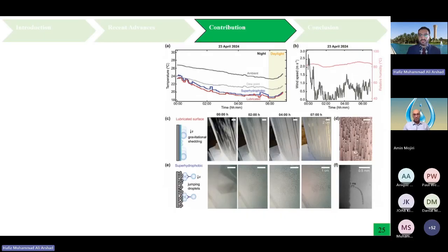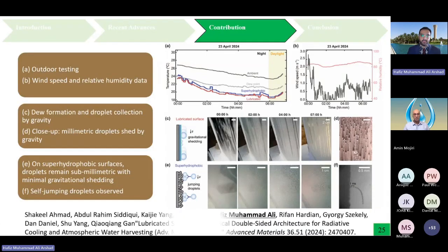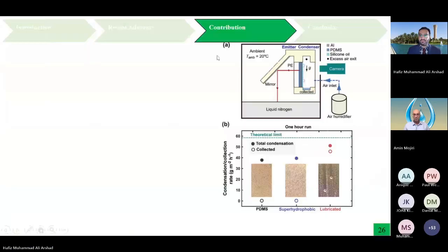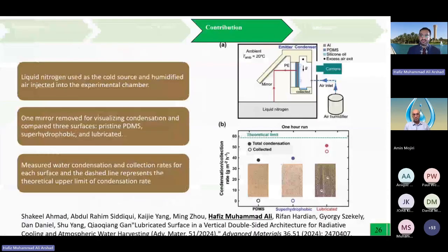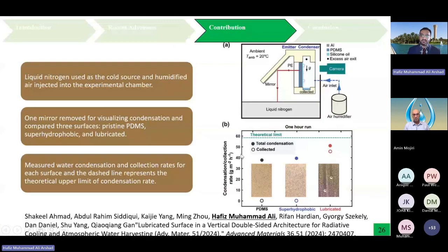Okay, right. I think this is a very good question. Here you see that we have one test that we have done where the relative humidity was over 80%. The water collection outdoors, as we have shown, was almost 21 grams per meter square per hour. We have also done some indoor tests, where the relative humidity was changed. The tests shown here are inside indoor conditions where the relative humidity was almost 50 to 60%. Even at that relative humidity, the collection rate was really high. As you can see here, when we have a lubricated surface, it went up to 50 grams per meter square per hour. Now looking into the cost analysis, which we have already done.